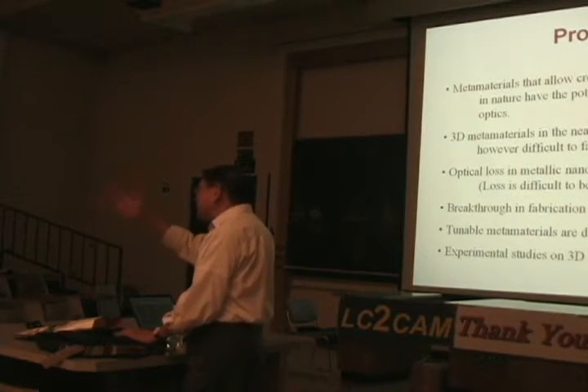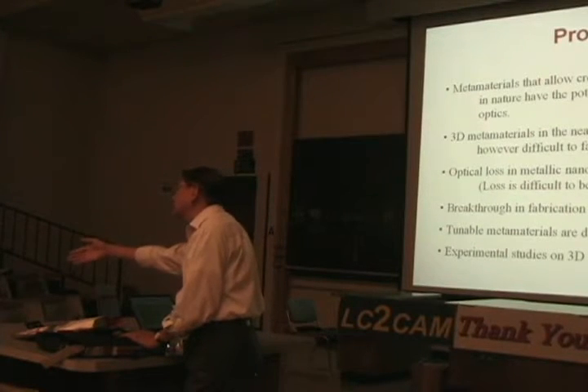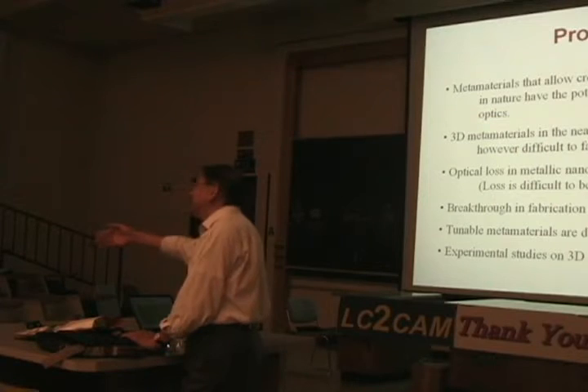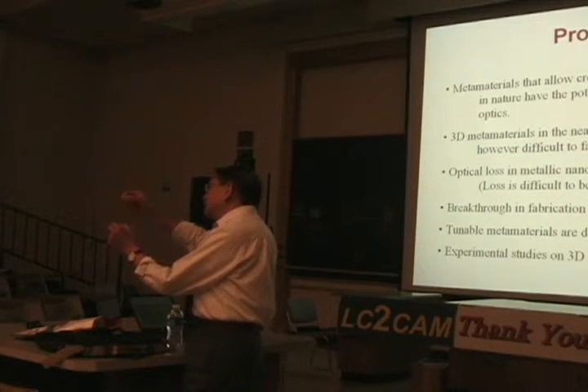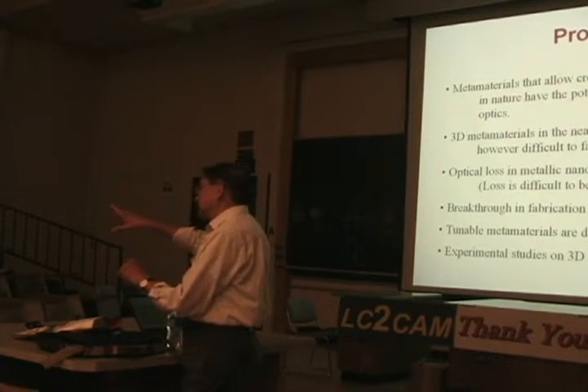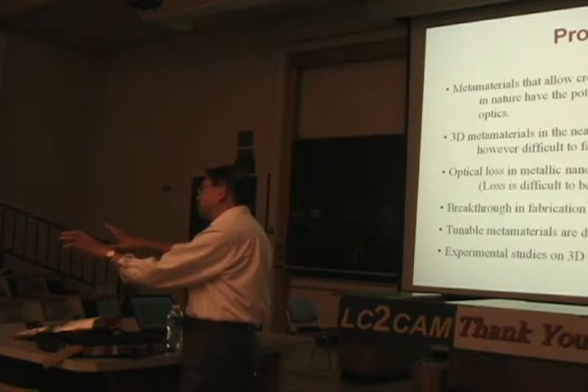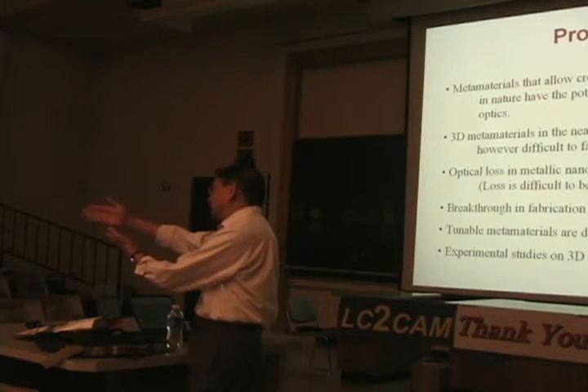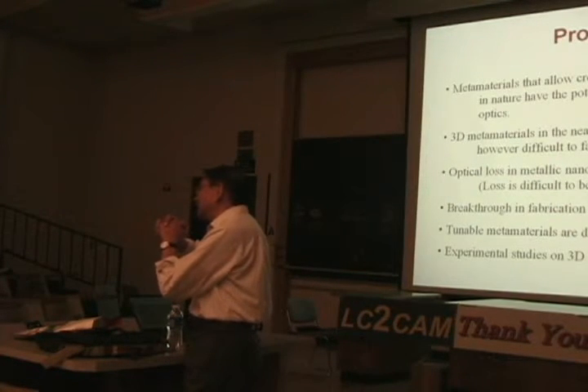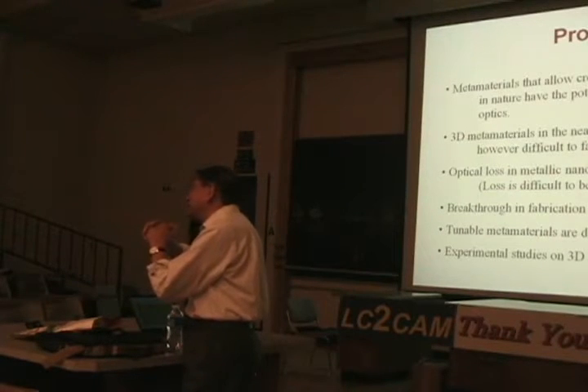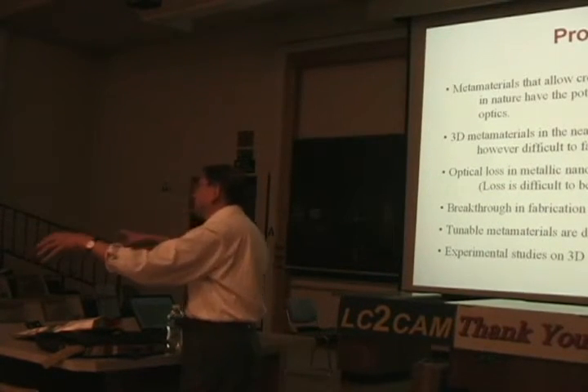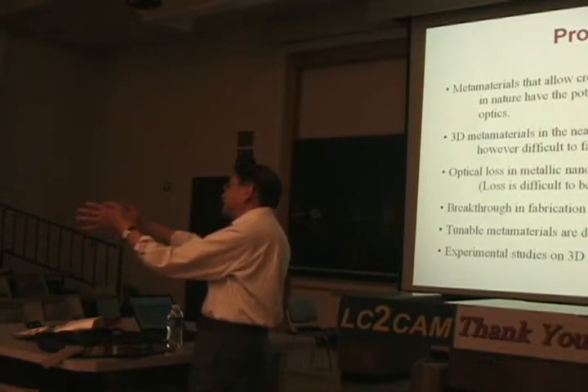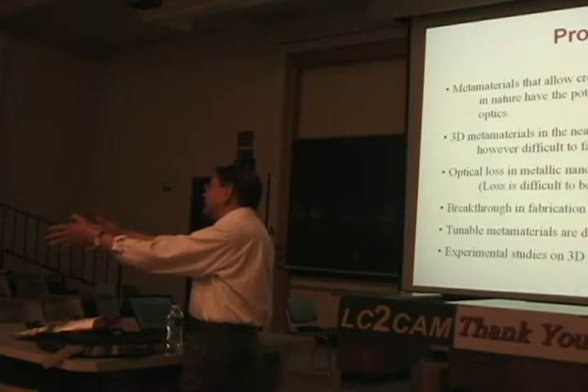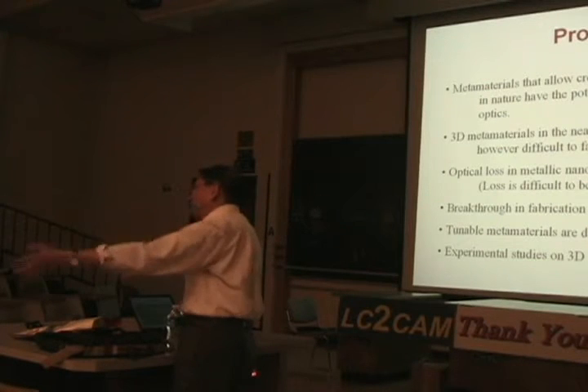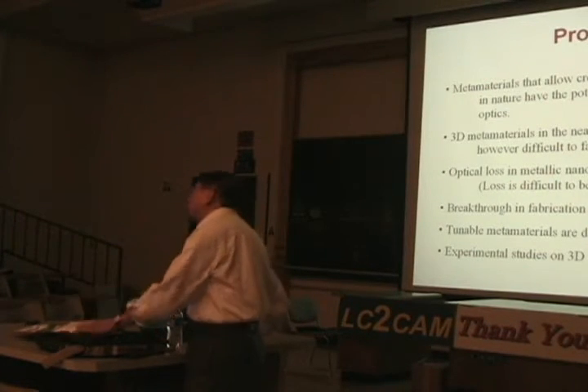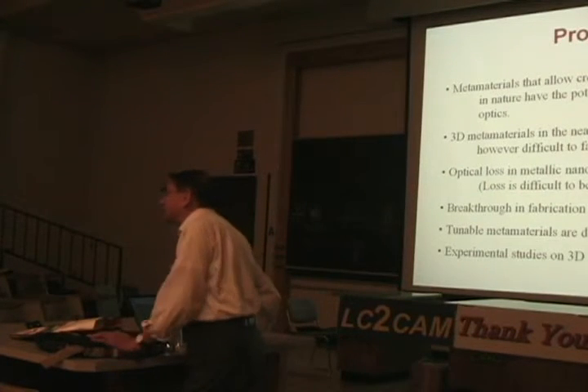So you don't say, because the evanescent wave cannot propagate. If it cannot propagate, it cannot carry energy. So it's really just, at the beginning, there is a transient period for this field to redistribute. During that very short period, you don't have the so-called evanescent wave or negative refractive index. It just tries to adjust the field distribution. And once it establishes the field distribution, it basically says, this is the field pattern for that particular system. So it's very similar to the optical tunneling case, and that's always difficult to explain to the students.